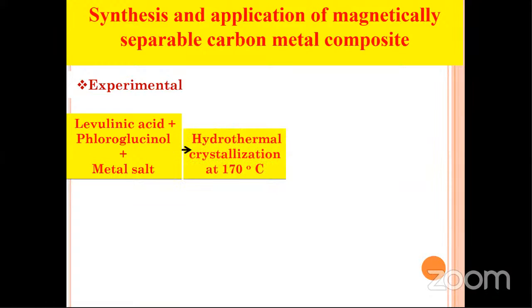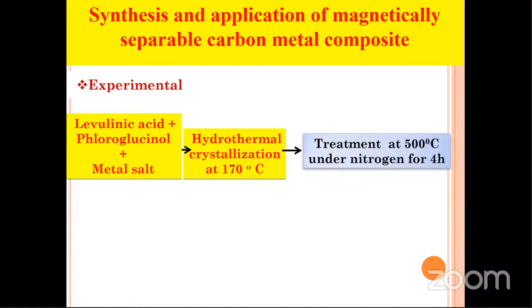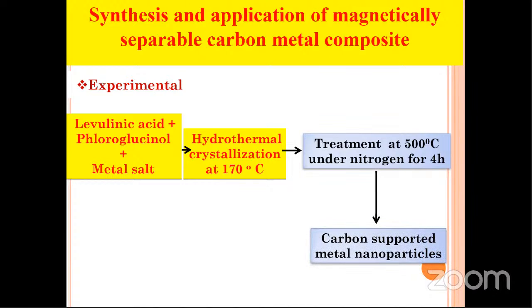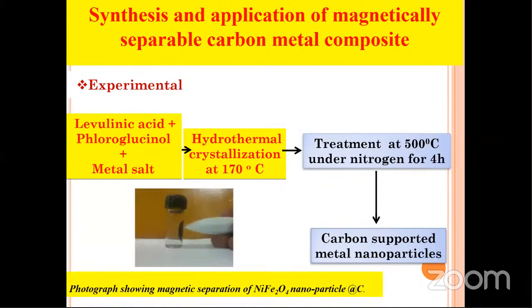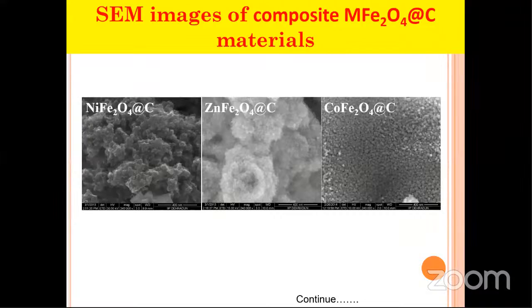These precursors were mixed together in a beaker. Upon hydrothermal crystallization at 170 degrees centigrade, we get a solid polymer, which upon treatment at 500 degrees centigrade under nitrogen for 4 hours gives magnetically separable carbon supported metal nanoparticles. Here you can see how this material can be separated by a magnet. You can see the photograph showing magnetic separation of NiFe2O4 nanoparticles on carbon. These are the images of the material, showing how the nanoparticles look.